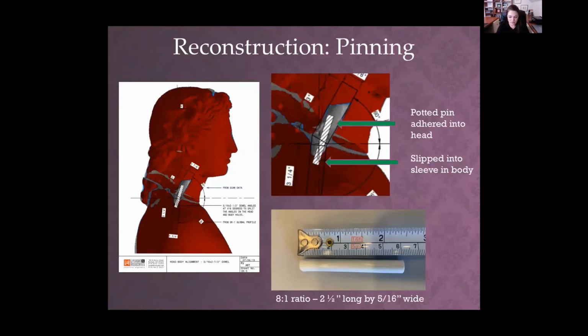But pinning the head was quite an ordeal. So we used a lot of Andy's knowledge of engineering. He created the 3D head body alignment picture here on the left. And what was interesting is that the hole going into the head and the hole going into the neck were not matching up in alignment. It was not a straight line. And so it became very clear that we were going to have to use something a little bit smaller than what was available there. And in Linda Roundhill's conservation treatment, she mentions that she removed one very large copper alloy pin bent in the middle, secured into the hole in the bottom of the head with tightly packed sulfur. So unfortunately, we don't have the pin itself that was removed, but we realized that this is why it was bent, because these holes did not have correct alignment in a straight line.